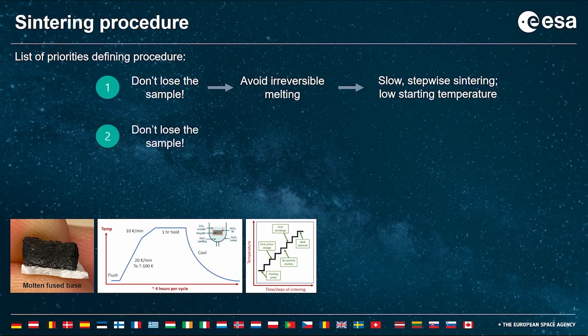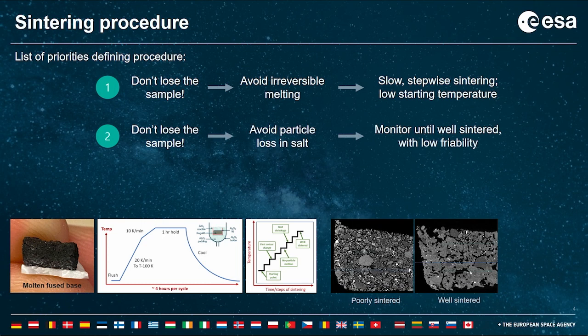The second priority was, don't lose the sample. And in this case, we really wanted to avoid particle loss into the salt in the next stage of the experiment. And so for that reason, you can see the two examples there of XCT images of sintered pellets. These actually look very similar on the outside, but you can see they're structurally quite different. And the one on the left there, there's a lot of particles loose on the surface still, and it's very loosely sintered together. And so as we introduce that to the salt, it would likely crumble apart and we would have more particle loss. So we were aiming for a very well sintered material.